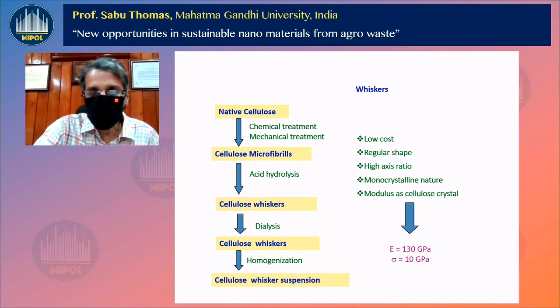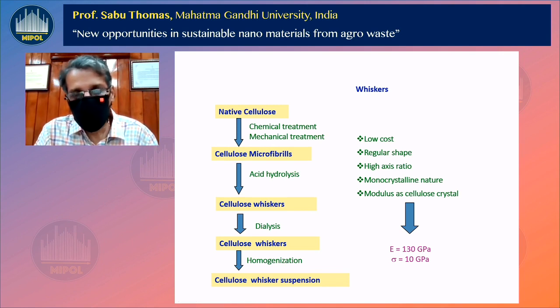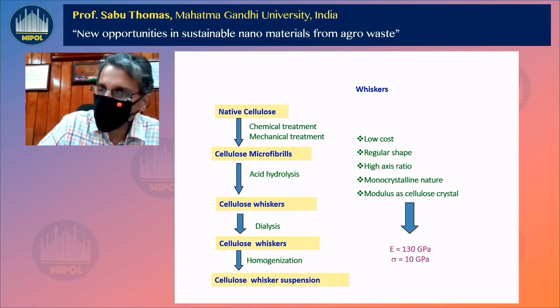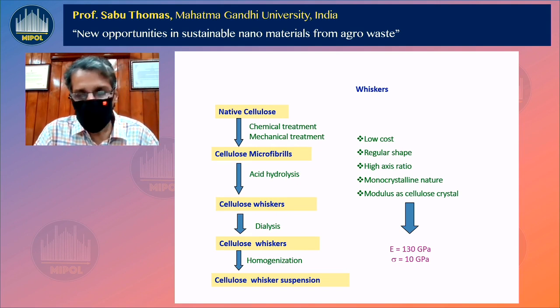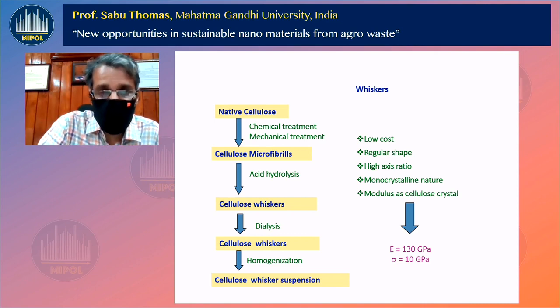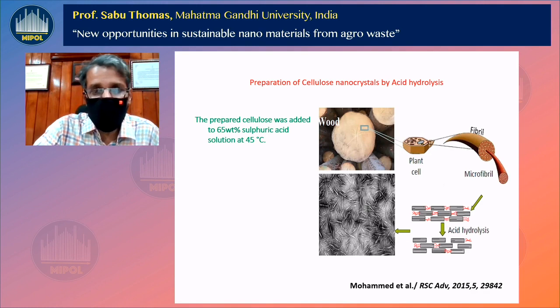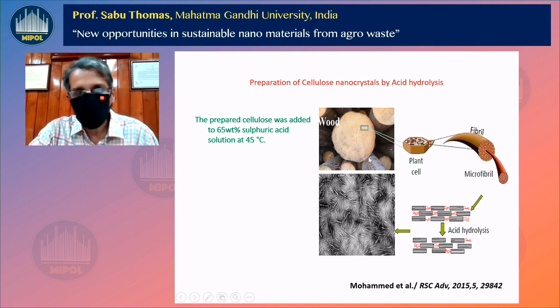The beauty of this material is, look at the modulus, 130 gigapascal. Look at the strength, 10 gigapascal. For typical polymers, the modulus is 2 or 3 gigapascals. You can improve this by putting this material into polymers. Look at their low cost, regular shape, and high aspect ratio. Look at these nanocrystals made by Mohammed, by strong acid. He used sulfuric acid, 65%, at 45 degrees Celsius. Mohammed made beautiful nanocrystals from wood flour.